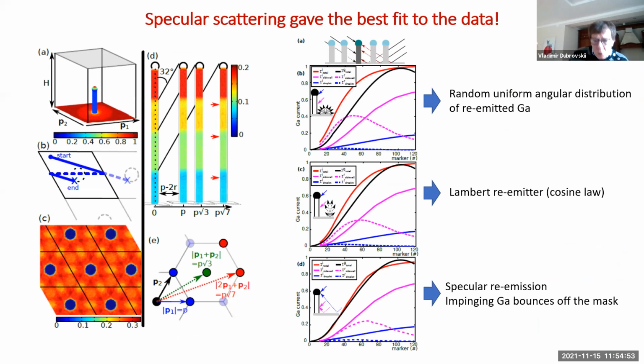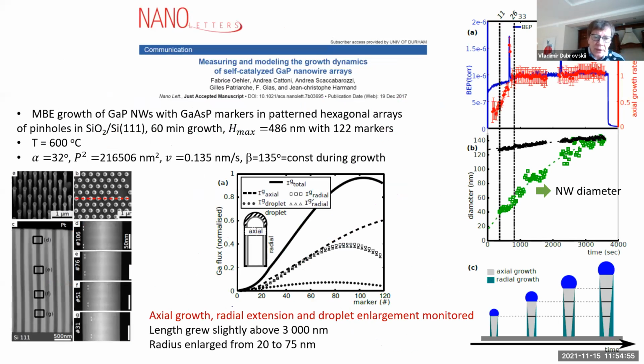And then what was measured, most importantly, is this curve, which is the total gallium flux onto the wire, including the droplet, which started from 0, and then it reached the maximum, and the maximum flux is simply given by the area per nanowire in this particular array times the growth rate V.